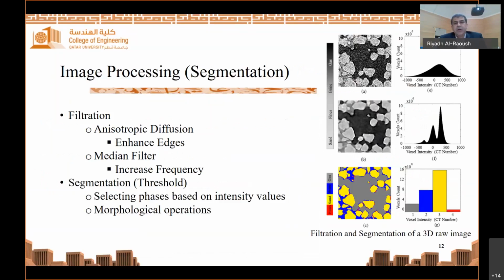Once we have 3-dimensional images obtained from computed tomography, image post-processing and segmentation are needed to convert grayscale images to binary images, so we can work with them and do some quantification. There are many segmentation algorithms available that can be used to achieve the segmentation step. Also, there are different filters that can be used to enhance the quality of the images. For instance, in this case, we use anisotropic diffusion and median filters to enhance edges and boundaries of the phases before the segmentation step.